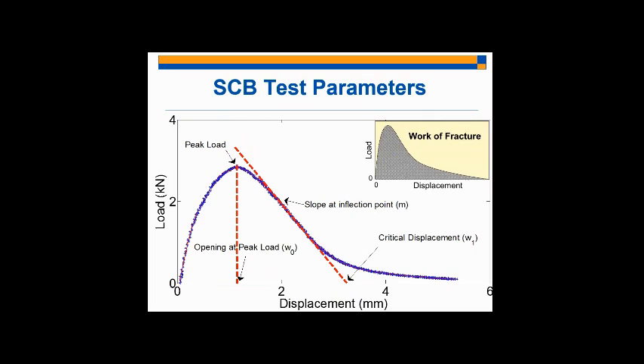So what am I talking about here, right? What typically happens is you get a load displacement curve, and you would calculate the area under this load displacement curve, which would result in the work of fracture done. Then you normalize this value by the ligament area, and that gives you the fracture energy. So very simply, the fracture energy is just the area under this load displacement curve normalized by some specimen dimensions.